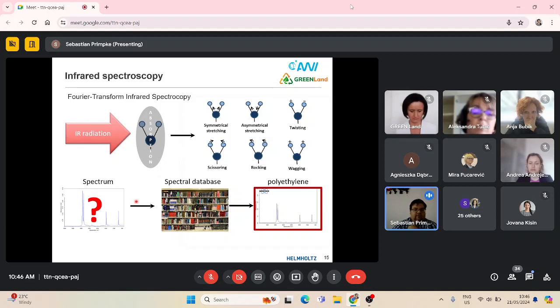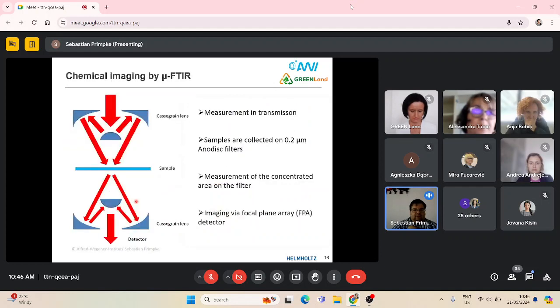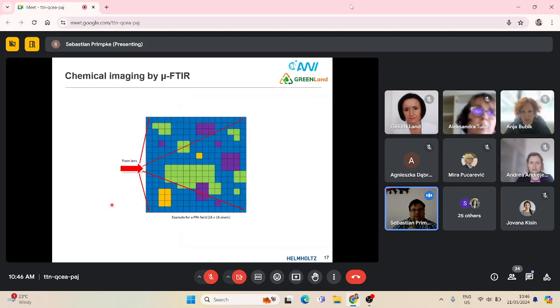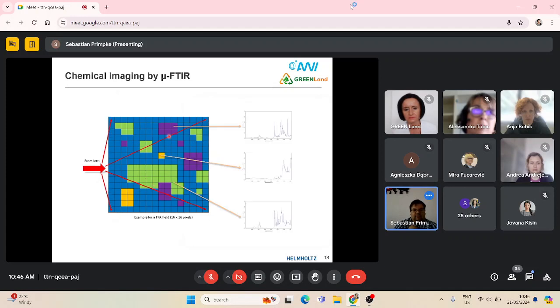What's good about this, as we already heard, is that it is especially useful to identify the different identities of a spectrum. So I will skip this slide. And what we do here is we work mainly in transmission, having the sample in the middle of our sample beam, and then everything moves to a detector. In this case, it's a focal plane array detector, meaning I get a chemical image, which looks exemplified like this, and in each dot we have a spectrum, which we then analyze.